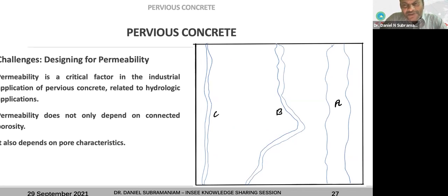And then when we talk about permeability, in the previous picture, I said that if the pore is actually connected from the top to the bottom, then it will contribute to permeability. But the problem is the permeability as a number does not depend only on the connection. It also depends on the size of the pore, right? Because of the capillary effect and surface tension, everything is going to play an important part. So it's not a linear relationship between the size of the pore and the permeability. Permeability is a big question even in unsaturated soil mechanics. We don't usually teach that in university, and sometimes we tend to use it as a constant. Right? But the actual fact is that you should be able to model it with probability distribution functions, right?